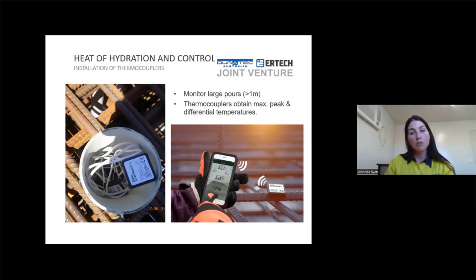The temperature sensors were from a company called SmartRock, or Giatech SmartRock sensors. Basically, you download an app on your phone, the SmartRock app, and install the sensors in the rebar at 3 different locations: one, say, 300 mil from the bottom, one in the middle, and one 300 mil down from the top. So we're getting the bottom, middle, and top temperatures throughout the concrete, and it's monitored every 30 minutes for 120 hours.